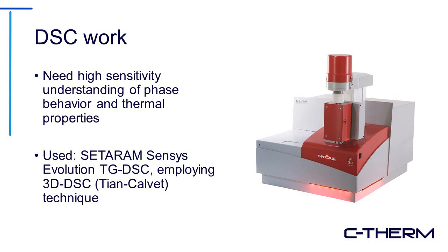And the cylindrical heat flow sensor has a number of different advantages to it. The biggest one is that because it can pick up, or detect rather, both convection and radiation in addition to thermal conduction, whereas a traditional flat pan-style DSC is only able to detect thermal conduction down into the sensor. This kind of heat flow sensor winds up being much more sensitive to small heat effects, as the overall heat flow sensor efficiency is in excess of 90%, whereas with a traditional DSC, the heat flux DSC sensor efficiency is going to be on the order of 35 to 40% at best.